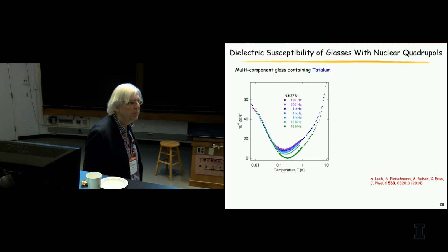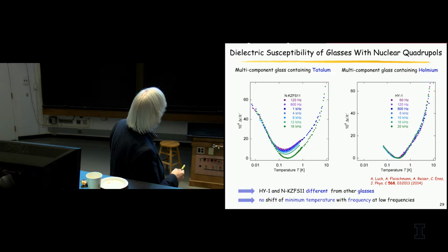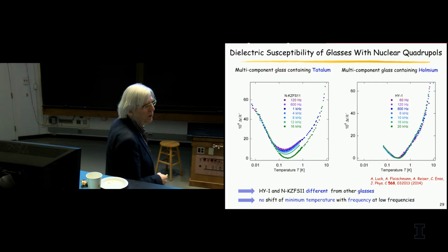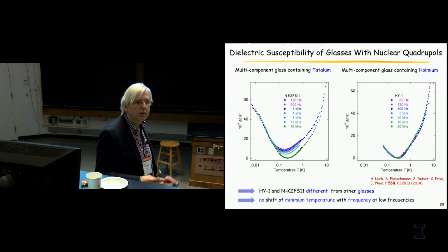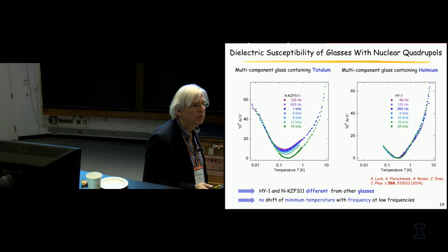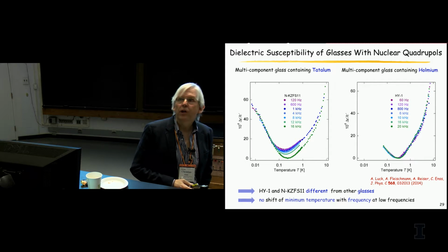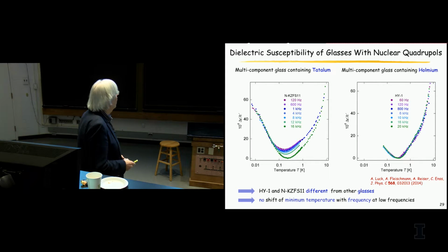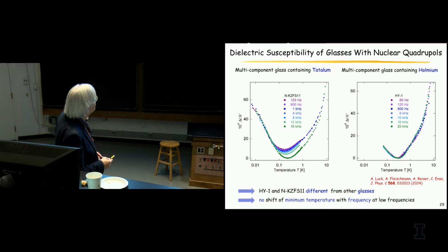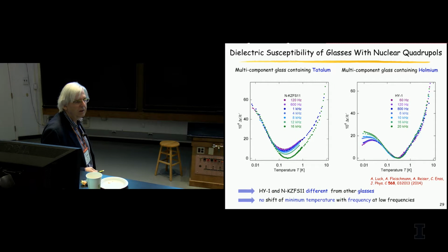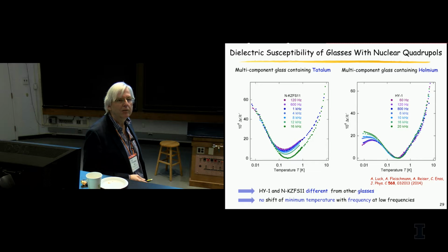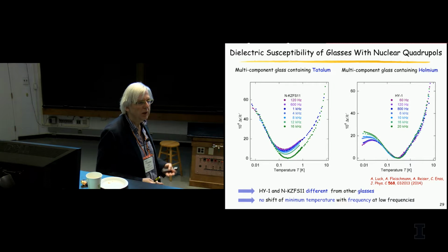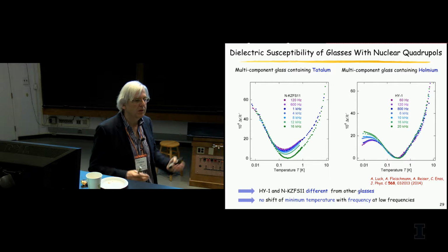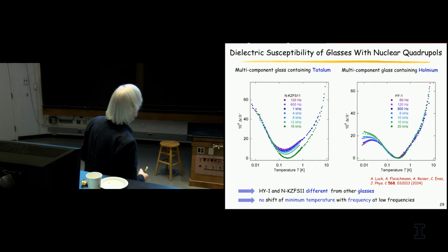And even more bizarre, if you go to the holmium glass, it seems to be completely inert about the phonon relaxation. It doesn't shift anymore. And if you now measure to lower temperatures, something very bizarre happens. It becomes frequency dependent again at the lowest temperature, which it shouldn't, because the resonant process shouldn't be frequency dependent. So something very odd is going on here.